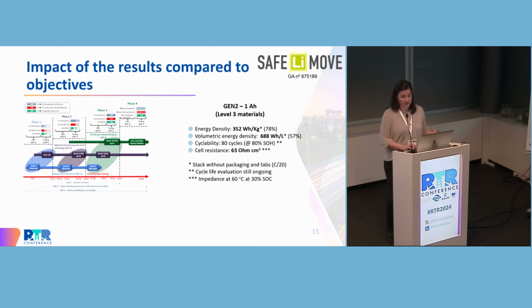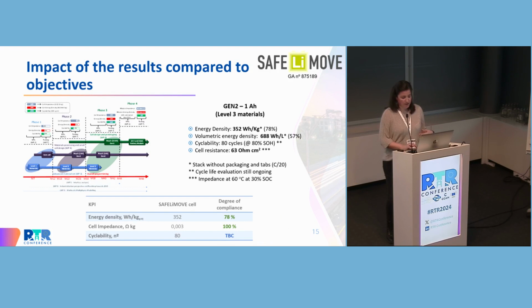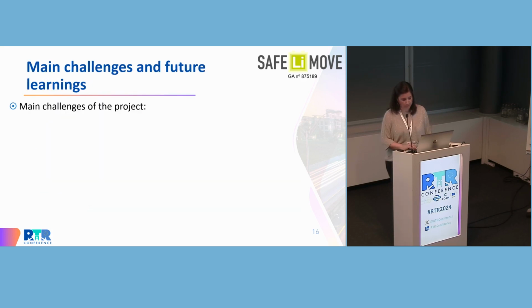And if we compare to defined KPIs, we can see that in terms of energy density, we reach 80% of the energy density. In the case of the volumetric energy density, we are below. We are around 55, 60%. In terms of the cell impedance, we have fulfilled the target. And then the cyclability, as I was saying before, this is a value that is still ongoing.